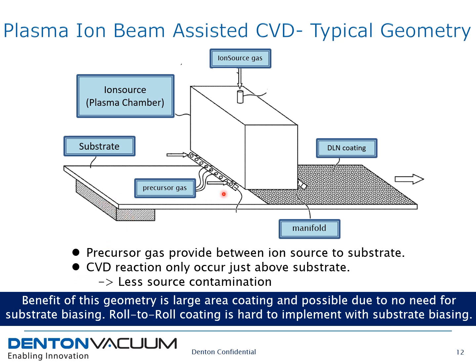Since there is no need for substrate biasing, the source can be used in an inline system as is shown here. The main advantage is large area coatings at low substrate temperatures, so it is very suitable for roll-to-roll coatings on flexible substrates. Since the precursor gases are delivered outside the source, there is less source contamination and longer operation times between maintenance. Now, this type of geometry is possible only because there is no need for substrate biasing. In fact, roll-to-roll coating would be very hard or almost impossible to implement with substrate biasing.